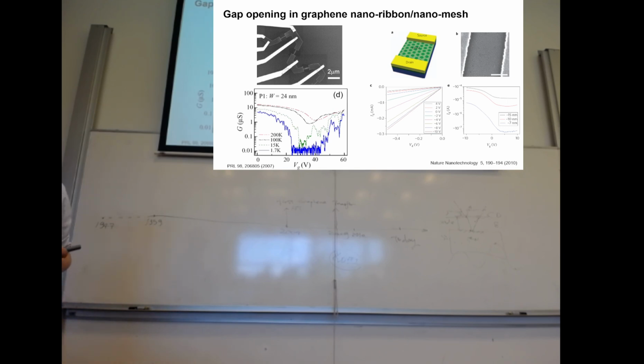Also, there is another paper in 2010. People managed to etch graphene into arrays of holes, so it's not a continuous film anymore. It's just arrays of holes etched on top of graphene. The good thing is that the IV curve still looks ohmic, so it's still conducting. Meanwhile, the Dirac cone is killed, so it's not a very sharp bipolar behavior. Instead, it's on and off, like a semiconducting field effect transistor. The only thing is that here you have only an on-off ratio of 2 orders of magnitude, which is not very good for application purposes.